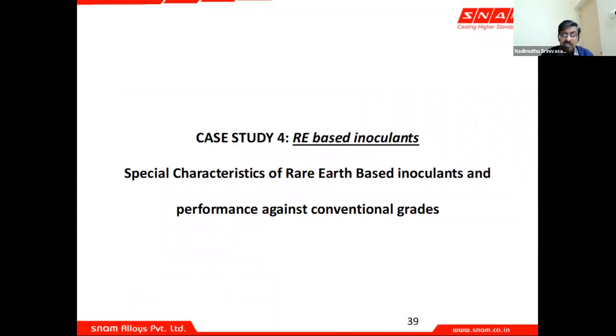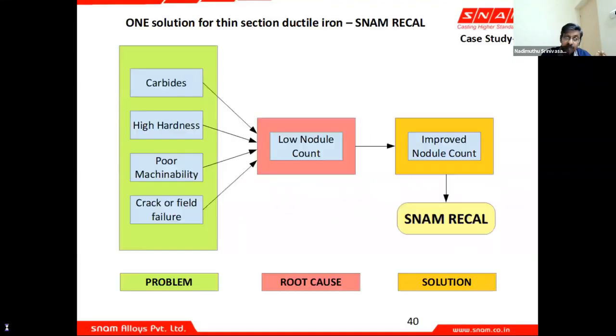Next case study is on rare earth based inoculants. Not recommended in all cases, but there are typical cases where we recommend the use of rare earth based inoculants. A thin section ductile iron is a typical area where a rare earth based inoculant is called for. So you have carbides in a thin section, you have high hardness in those areas, you have poor machinability, and you can also have a crack in those areas because of all these reasons.